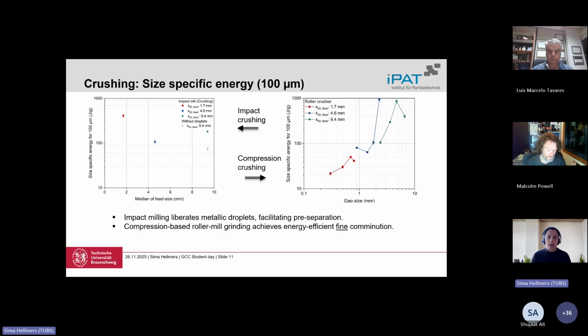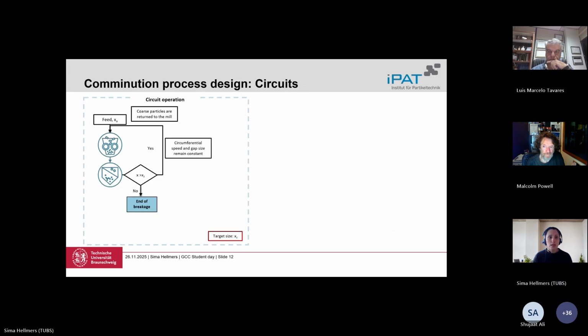If we look at the slag, we can see that there were metal droplets, and with the first impact, we could get these metal droplets out of the system, and then after sieving, we had the slag on its own. So we can say that we can use impact milling to liberate these metallic droplets and facilitate our pre-separation. And then we use a roller mill to reduce the gap size step by step and reach our target size. So let's look at the comminution process if we had a circuit for the fine grinding.